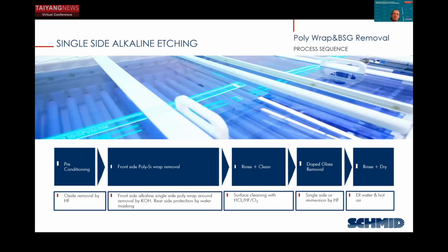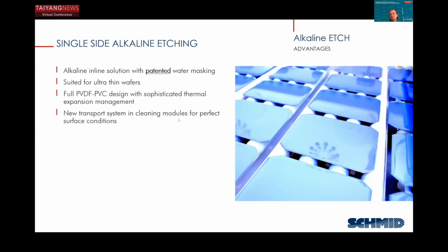The same system works very similarly, of course, for the poly wraparound and BSG removal, or dope glass removal, I should say. You do again a preconditioning. You do a poly wraparound removal, single-sided, rinse clean, dope glass removal. Then, depending on the process, again, you use a rinse and dry. So this system is using a patented water masking, which we have worldwide as a patent. It is suited for ultra-thin wafers.